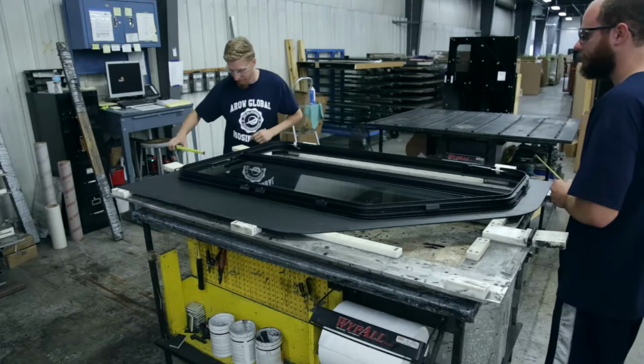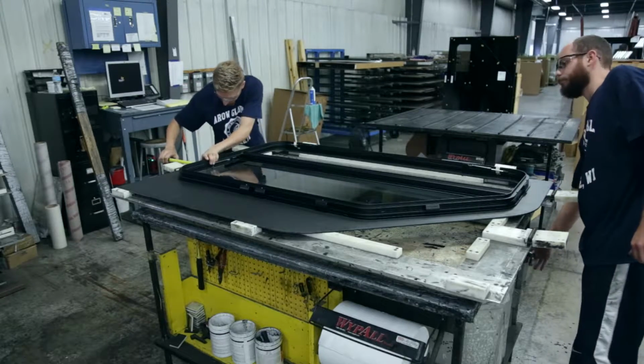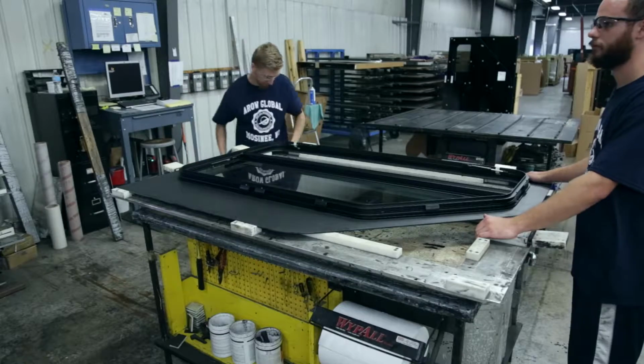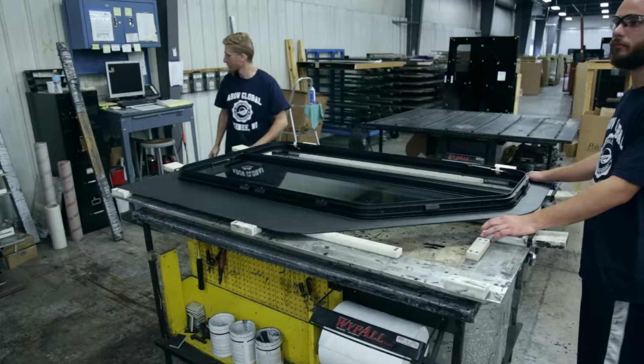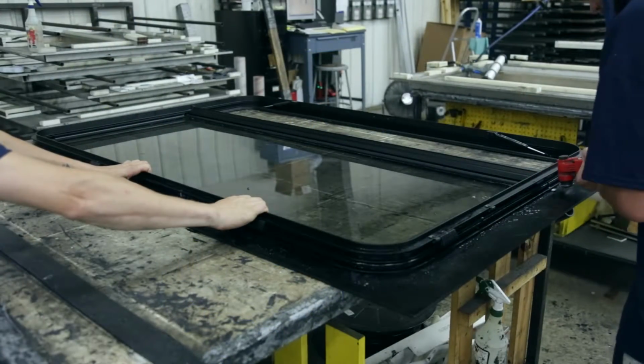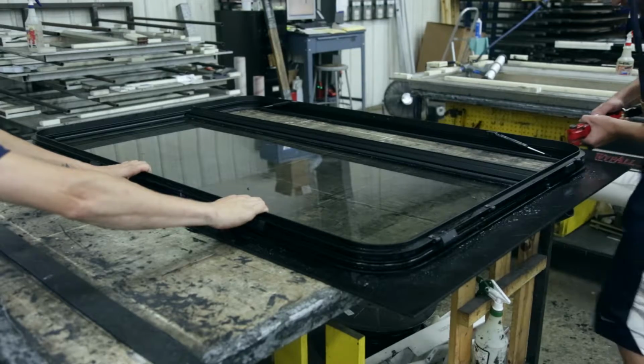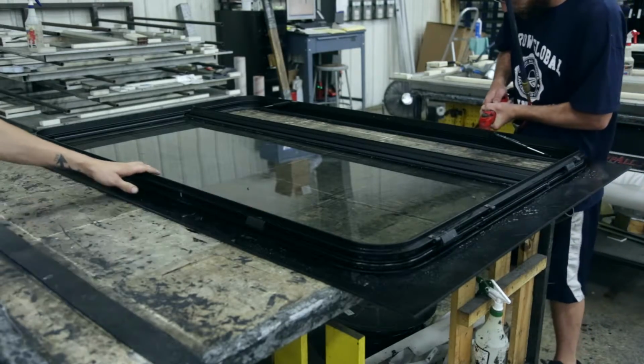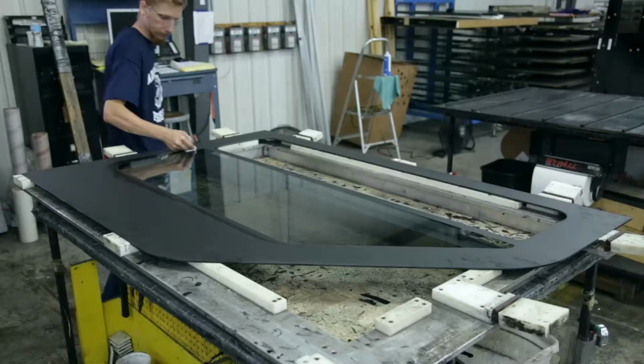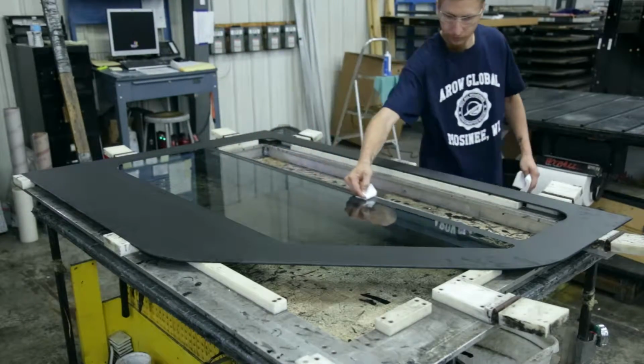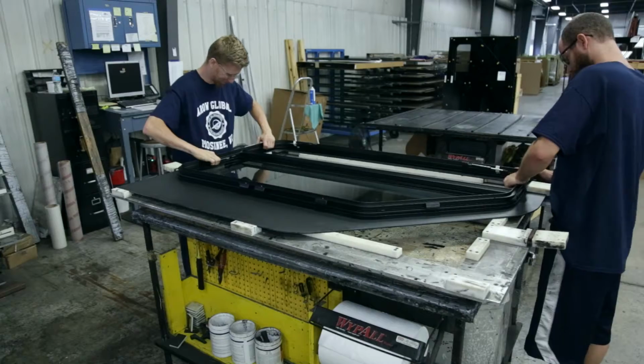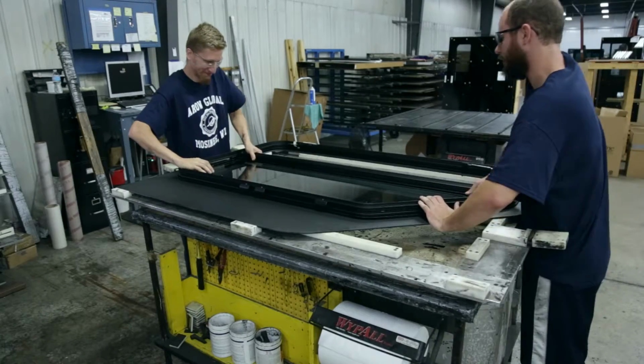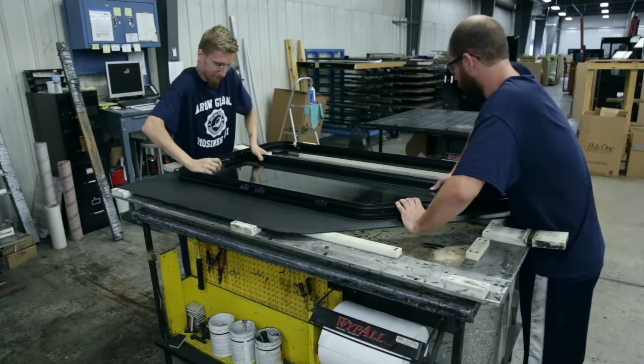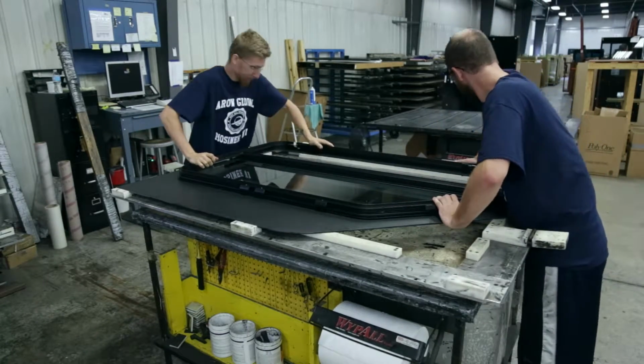Once the frame or hinge is set onto the glass, they must not be pulled away from the glass for repositioning. This will result in water leaks or a low-strength bond. If you place the frame in the wrong location and have to lift it off the glass to move it to the correct position, you must remove the adhesive, clean the bonding surfaces again, reapply the adhesive, and then position the frame back on the glass. It's okay to slide the frame into position after it has been placed on the glass if the movement is less than 1/8 of an inch.